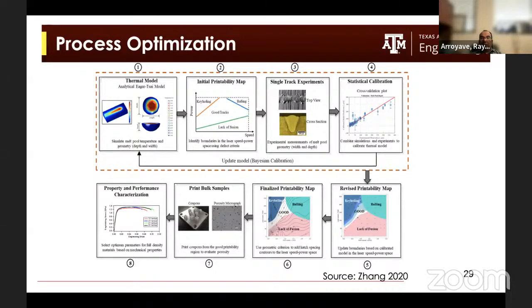So the first thing that we do is we say, well, we have this large processing space, we can change the power and the scan speed of the laser. Can we detect what regions in the processing space lead to optimal printing without defects? So the idea is we do some simulations, we compute some initial printability map, we do some single track experiments, we calibrate the models that we use to try to correct for missing physics. We revise the printability map, and then, in the good region, the region where we do not expect to have these microscopic defects, we print bulk samples.